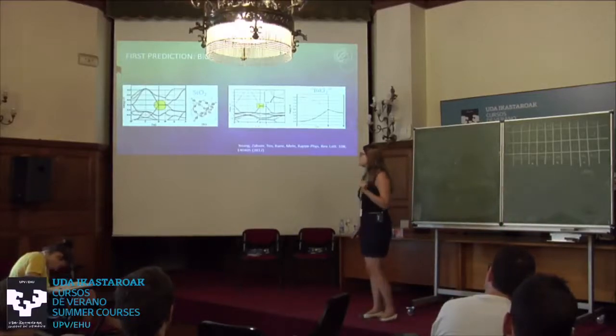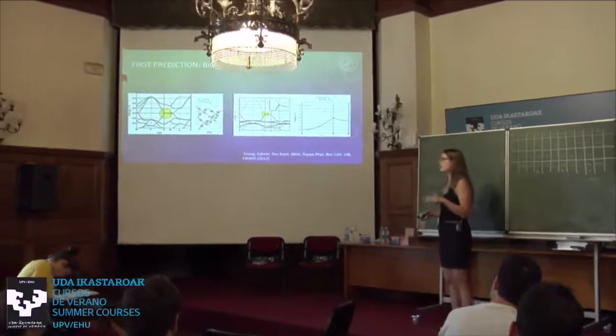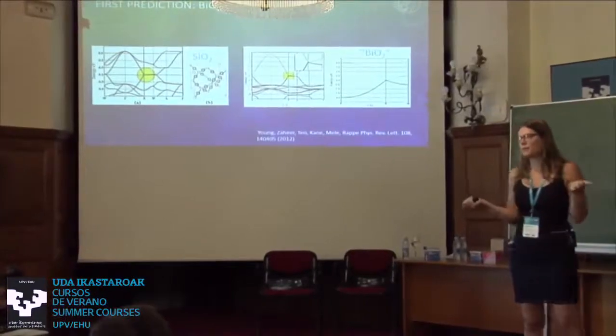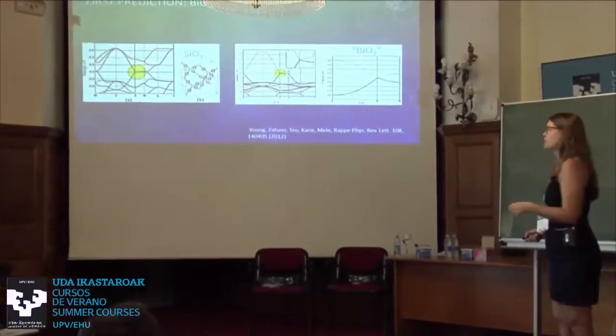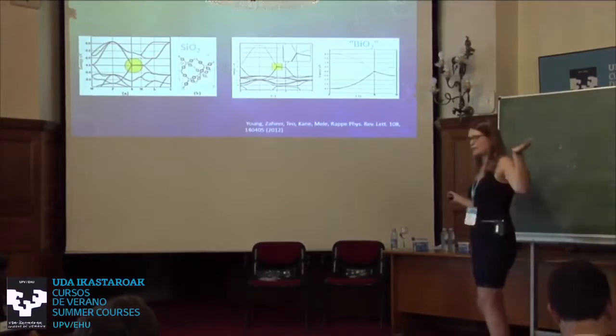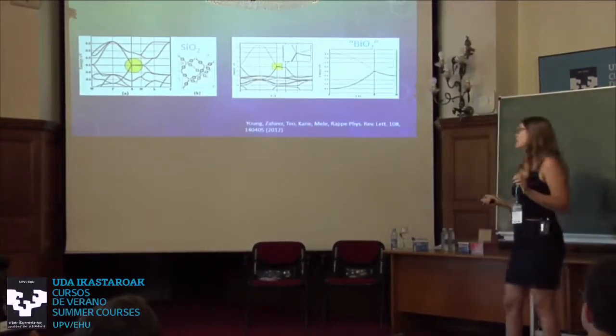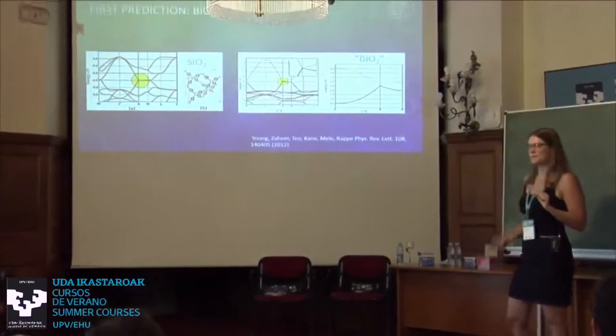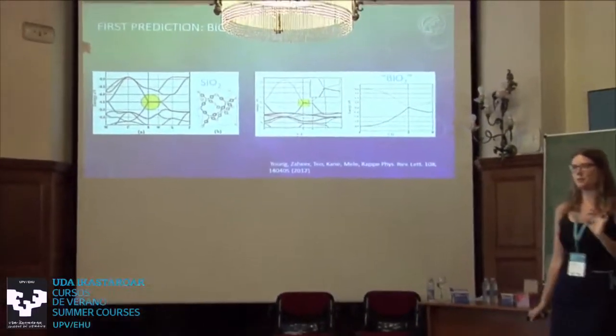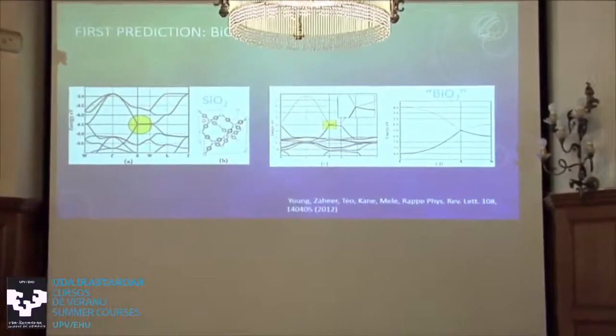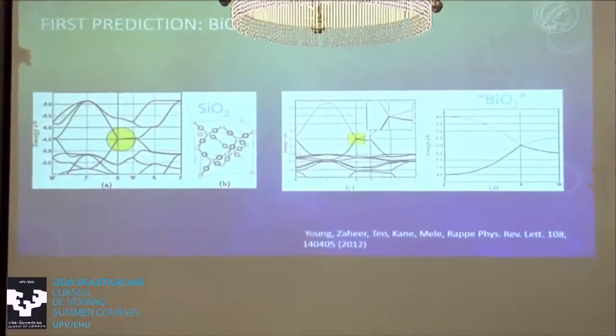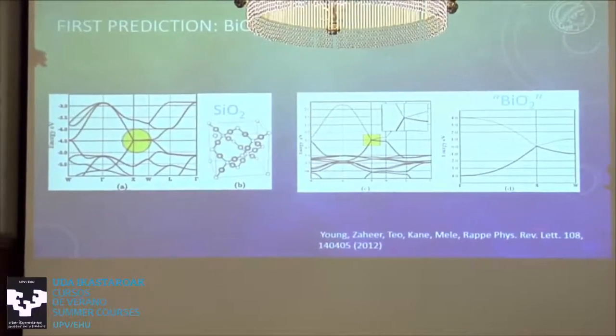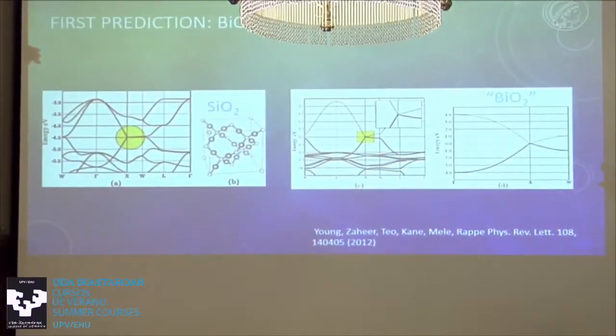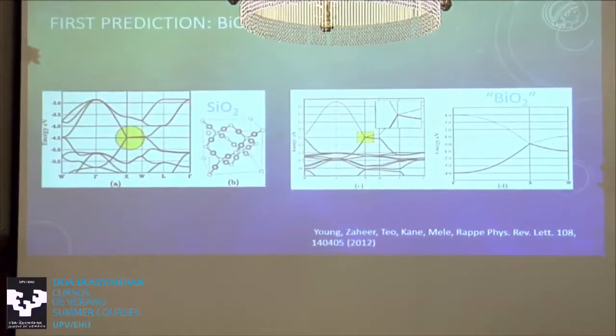And I just want to go, so there's one prediction, the very first prediction of the 3D Dirac semimetal, that has the problem of a half-filled band, and I just want to give you an idea, with the chemistry rules I told you before, why it can be so critical to just hand-wavy predict a material with a half-filled band. So first of all, I want to point out, I really like this paper. This is a really great paper. It was the first idea to use non-symmorphic symmetry to create those 3D Dirac semimetals, and it's a great theory job. The problem is that one material suggested here, bismuth O2, will sadly never be realized. And I hope I can make you understand why.